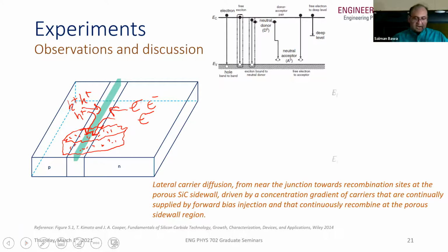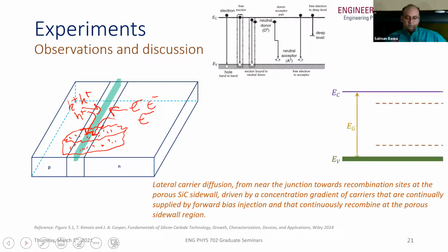Another way to interpret it is through the use of a band diagram where the defect centers are created within the band gap, between the conduction and the valence bands. The carriers diffuse to these defect centers where then they radiatively recombine.